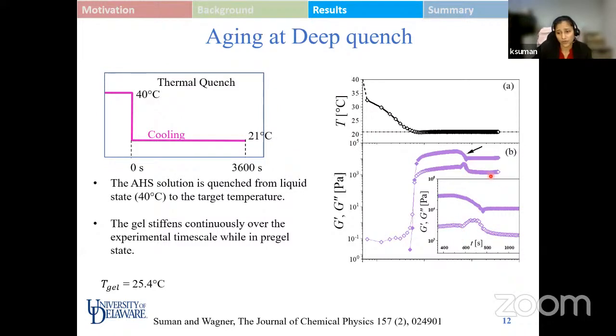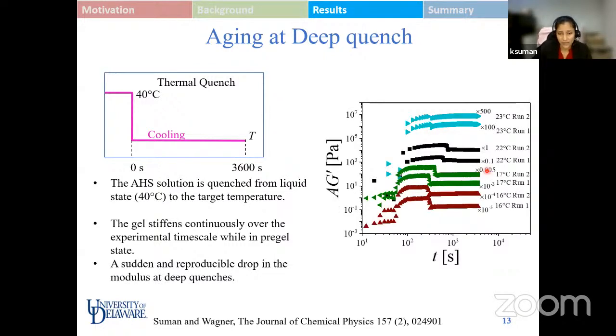Now, such a behavior where it shows a sudden drop in the modulus value has not been reported yet in the literature, and it is therefore very intriguing to study what happens microstructurally at this specific time and at the specific thermal quench. The first question is whether it is repeatable and happens at different thermal quenches or not. So we repeat the same experiment at different temperatures lower than the gel point temperature, namely 16, 17, 22, 23. And we can see that the sudden drop is very much reproducible on different